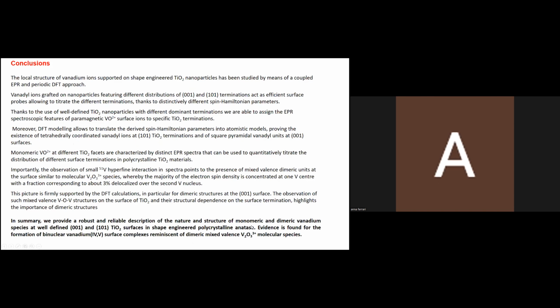So, to draw the conclusions, the local structure of vanadium supported on shape-engineered titanium dioxide particles has been studied by means of coupled EPR and periodic calculations. Vanadium grafted on nanoparticles with 001 and 101 termination can be used as a probe, since the adsorbed species are different, and these differences are reflected in the spin-Hamiltonian parameters, as I showed you.